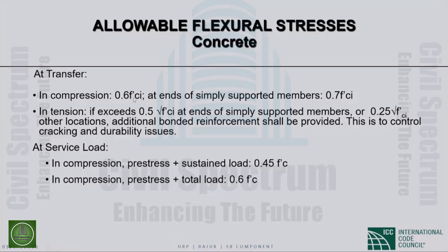Now, typically I've been finding from my practice that these values, the f'c and f'ci, are the as-built values. For example, if they give you a value in the as-built, you'll find out that if you do the cylinder testing, the results are typically quite a bit more, which is a good thing. Typically, we have been finding that the actual cylinder strength is about 30% more.